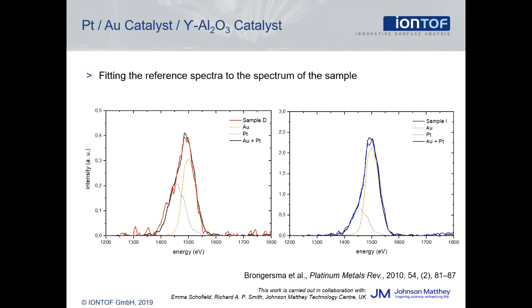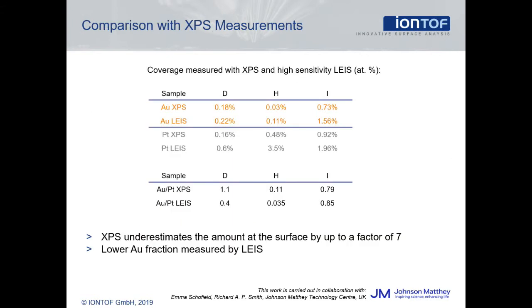Under the same conditions, the catalyst samples were also measured. Using the reference spectra templates for the peak shape, shown as dotted lines, the spectra of the samples are fitted. In other words, we look for the linear combination of the two reference spectra which best resembles the spectrum of the sample. The scaling factor for both reference spectra directly gives the coverage of platinum and gold on the sample.